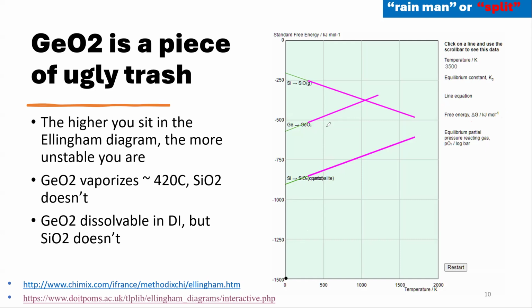When you go at high temperature, things go crazy, then it's not stable. I'm a process guy. That's what I'm worried about, right? For example, people find out GeO2 vaporizes at low temperature, 420 or less than 500, it will vaporize by itself. SiO2, on the other hand, is very stable. 1000, no problem, right? And GeO2 is dissolvable in DI water.